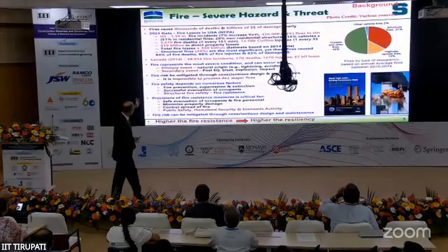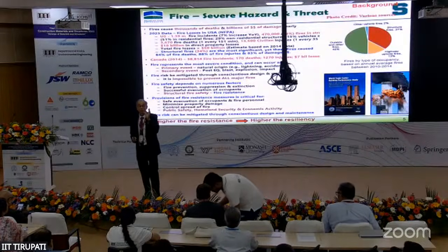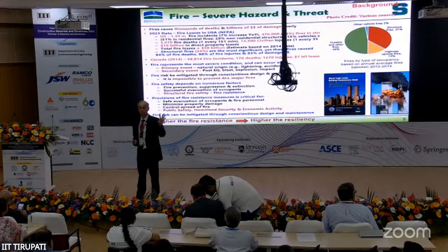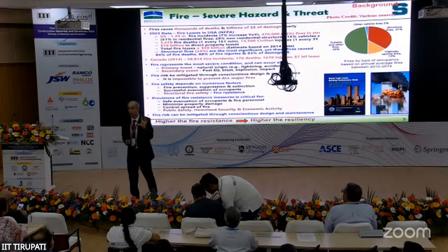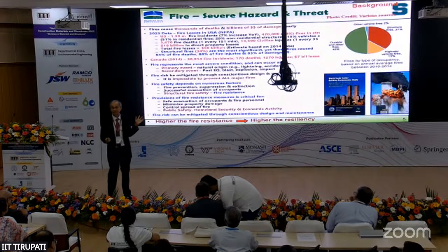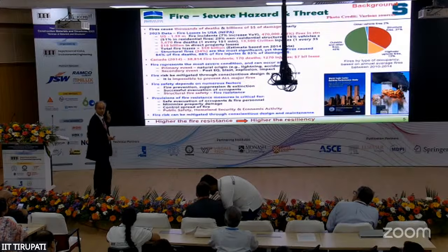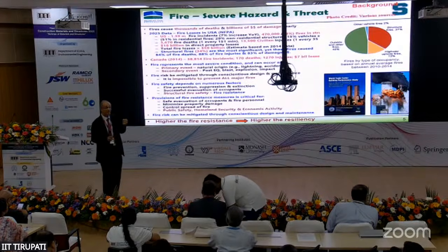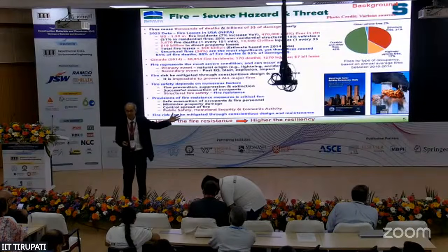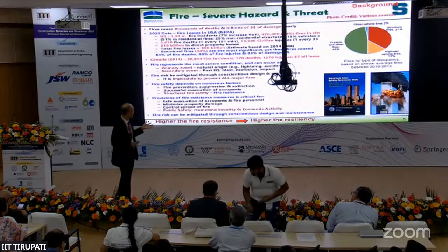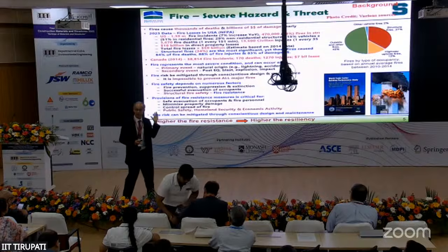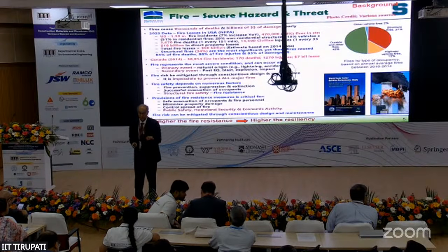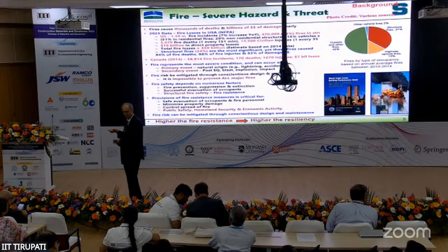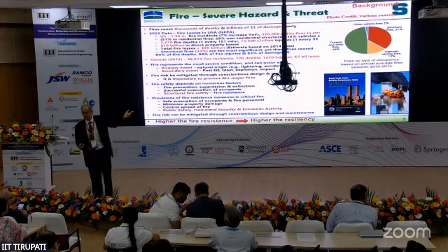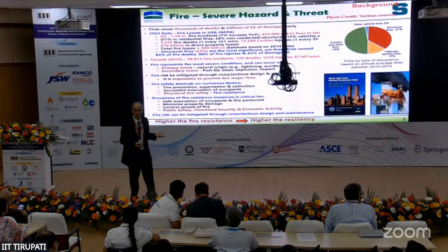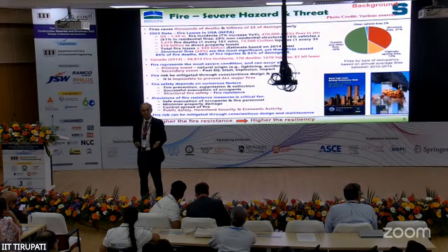Now, when fires occur, they represent the most severe conditions that a structure can see. Temperatures go up to 1,000 degrees, not 50, 60, 70, 80 degrees centigrade, 1,000 degrees centigrade or more. And it can happen from an electric short circuit, as simple as that, which is the common cause in India most of the time, or as a secondary event. After most earthquakes, you have a fire following, like the Kobe earthquake, for example, New Zealand, and the Chile earthquake. These are some of the recent earthquakes. It's followed by fire, or a blast leads to fire.